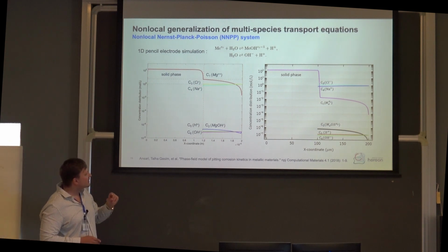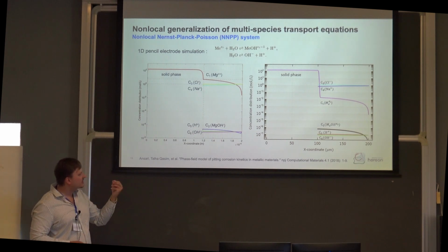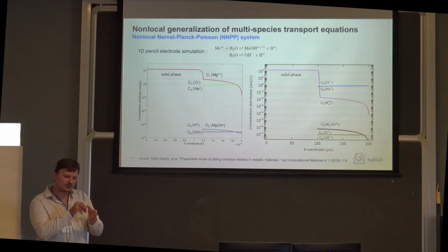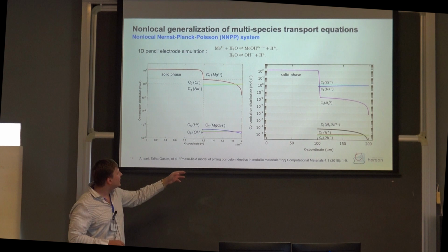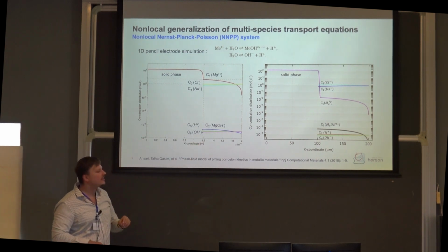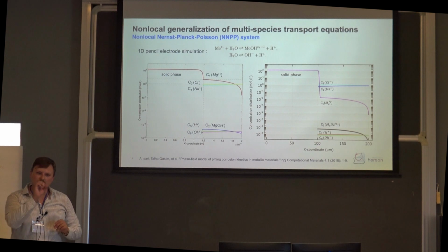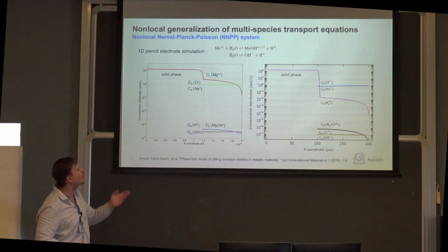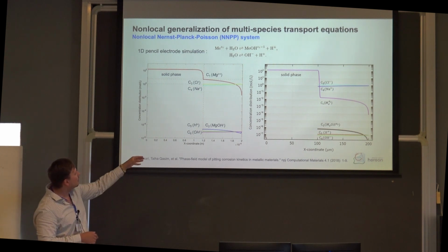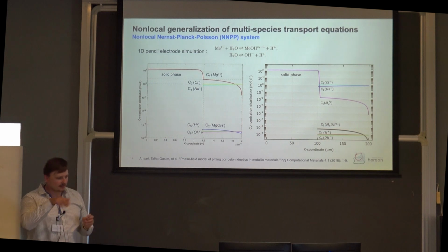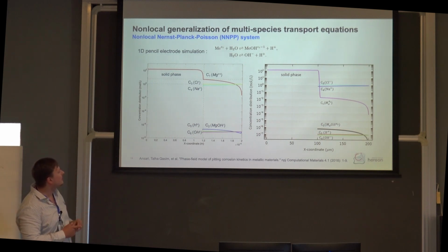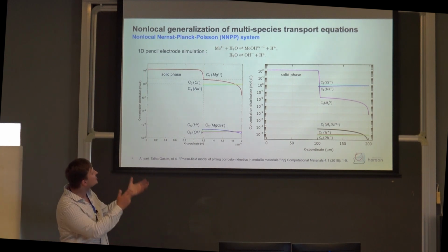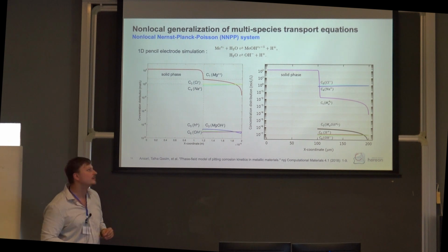One thing that we notice is that because we can select the micro diffusivities based on the spatial position of a node, we can modify it. Thus, if you look closely, we have discontinuities in these transitional layers and corrosion interface layers, which are not captured in the phase field model so far. So this continues while we have a kink here in the transitional layer and the interface corrosion layer. But in general, they should reproduce very similar results.